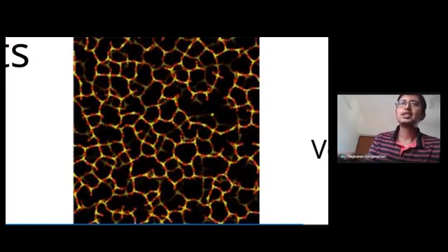What you see here is a silica glass. You can see the silicon and oxygen atoms shown by red and yellow. And what people have studied here is how a void forms in this glass and how it propagates as a function of deformation. And this is a small representative image, but now people can study what happens when a billion such atoms are there in the glass, right? So these are unprecedented scales at which people study these glass phenomena.